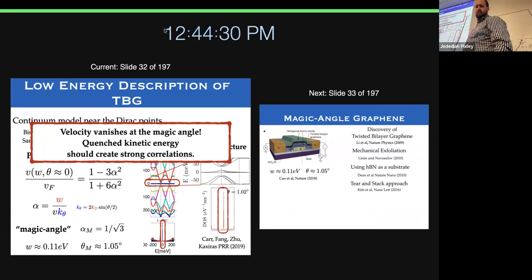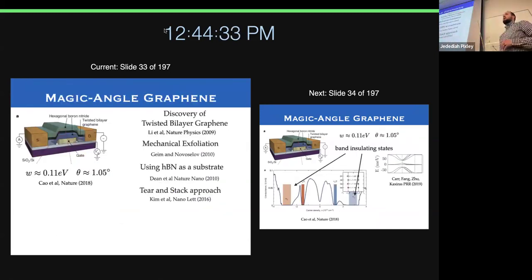And so what happened? There are several advances. Well, of course, there's the discovery of twisted bilayer graphene, by my colleague Eva. And then the mechanical exfoliation, this was in graphene. Mechanical exfoliation allowed single crystals to be exfoliated and have really nice 2D sheets. The problem was still using silicon dioxide as a substrate. It traps a lot of charge, introduces a lot of charge disorder. Then hexagonal boron nitride was discovered as this amazing substrate. Okay, it removed all the charge disorder, and now you have the so-called tear-and-stack approach, where you can take a sheet of graphene, rip it in half, and you know they're aligned, so you can twist them, and you can twist them to within 0.1 degree accuracy. It's an amazing experimental feat.